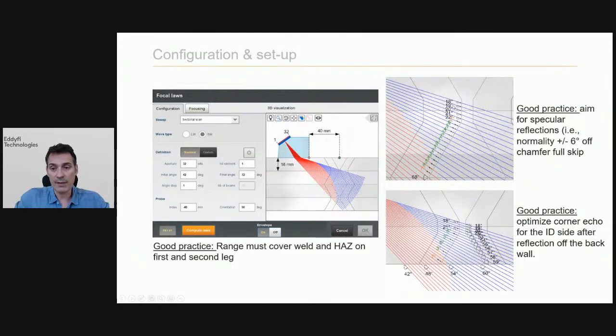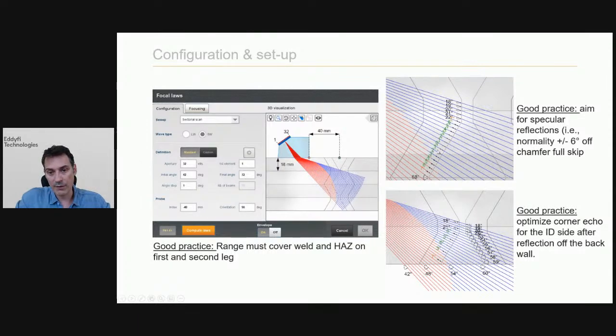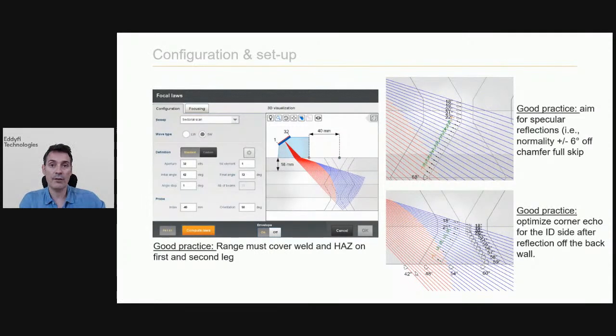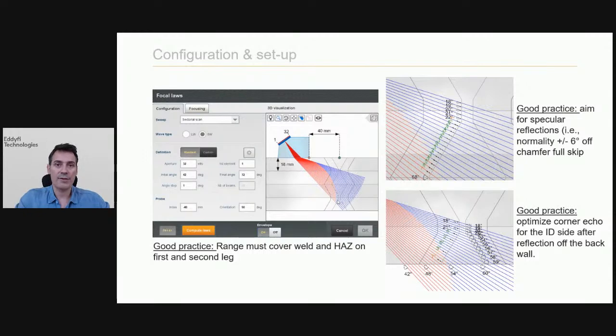By good practice, I mean when you do a sectoral, compound, or linear scan, you try to be normal to the bevel on the second leg. Standards tell you that you have to be normal plus or minus six degrees according to ISO standards. The scan plan in Capture is useful here because it displays the angle between refracted angles and the bevel, color-coded: if it's six degrees or less, it's green. On the first leg, we try to optimize corner echoes for root cracks or toe cracks. The range you select must cover the full weld and heat affected zone. The assisted analysis results are going to be as good as the acquisition.